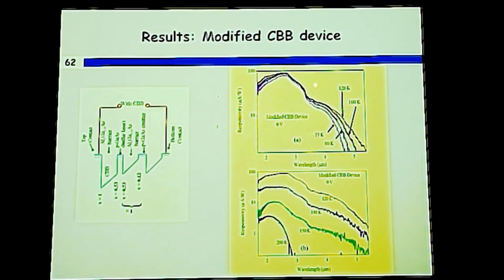So what we see here is we didn't see a drastic reduction in the photoresponse from 77 K to 120 K. Actually, it goes up slightly instead of going down. However, after 120 K, it again goes down, and we see the response up to 150 K in this one.